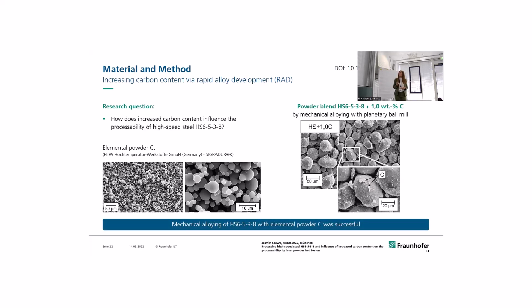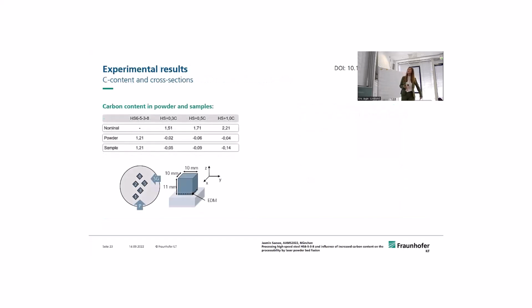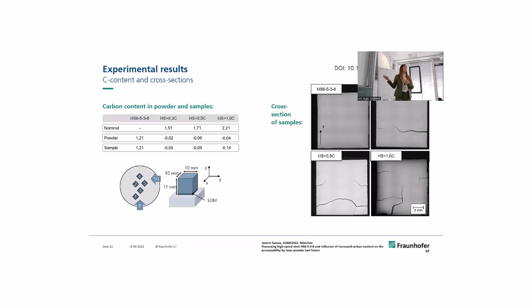And looking at the chemical composition, we even see that the carbon content that we wanted to achieve was achieved within the powder, but also within the samples. So the highest deviation we have is in the sample with 1.0% added carbon, and we saw in the process that we have a lot of spatters around, and we think that because of the fine grains, some of the carbon was transferred by shielding gas flow.